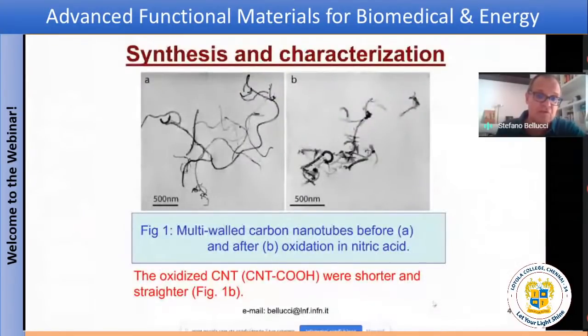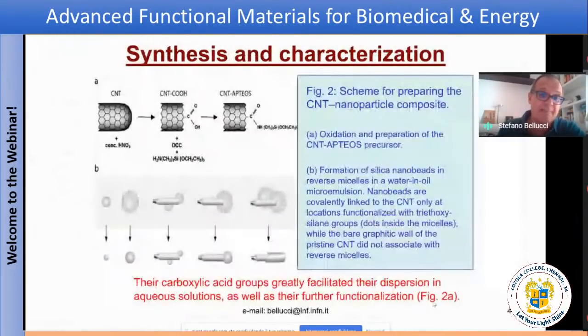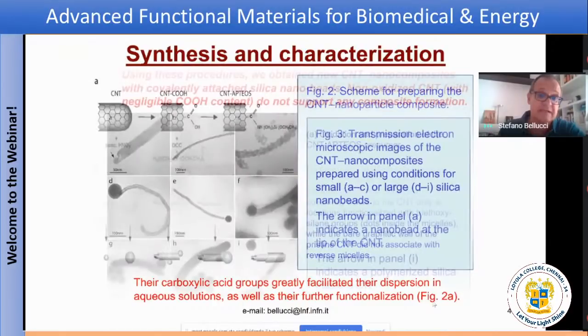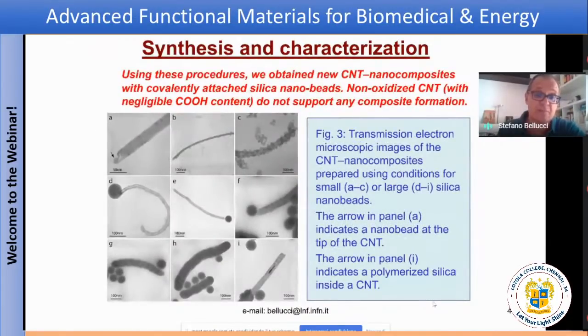We prepared short nanotubes, and we were able to practically engineer the length of these nanotubes by our recipe, and then use the carboxylic group, COOH, that we created onto the nanotube by functionalization in order to grow silica nanoparticles onto the different spots. The applications are, for instance, in magnetic resonance or in imaging for diagnostics. And here you see real pictures at the transmission electron microscope of the samples that we realized. As you can notice, you can have many different configurations of the nanoparticle of silica that then can be stained, can be colored, can be magnetized, can be a platform, and the nanotube.